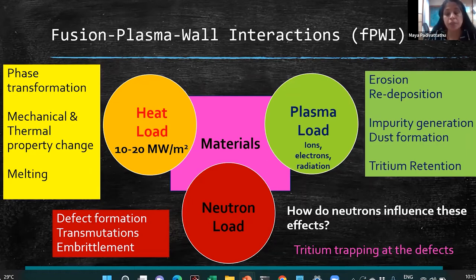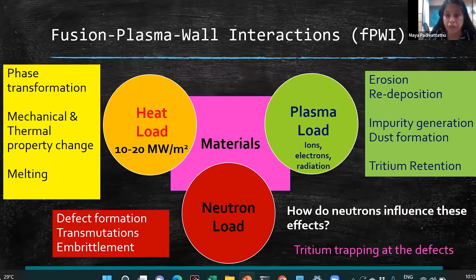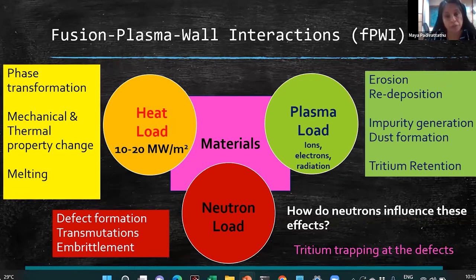Plasma ions can cause erosion by removing atoms from the wall and creating impurities. There are also radioactivity issues: tritium is a radioactive isotope of hydrogen with a short half-life, and it can become retained in the material. Neutron bombardment creates defects and transmutations — materials can capture neutrons and produce new elements causing gamma radiation. Another important issue is hydrogen embrittlement, where hydrogen in the material can cause cracking, which is dangerous from a nuclear safety viewpoint and is one of the major problems in reactor design.